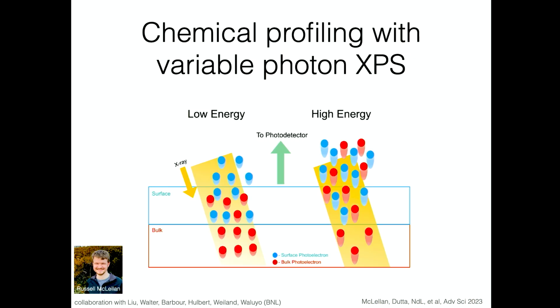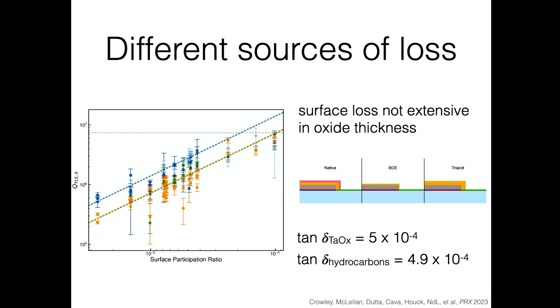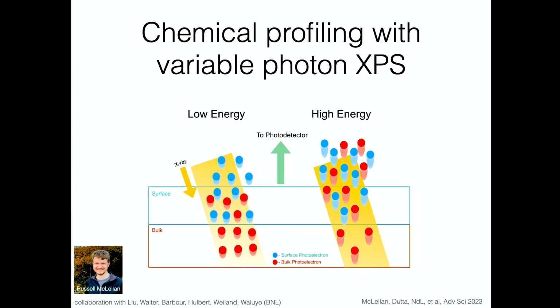All right, so I'm going to skip over the detailed modeling, but let me just say one of the puzzles that fell out of this is that we were trying to increase the surface loss. The natural surface loss is the surface oxide. And we were trying to increase the surface oxide to increase the loss. And what we found was that the surface loss was not extensive in the surface oxide thickness. So your most naive guess was wrong here.